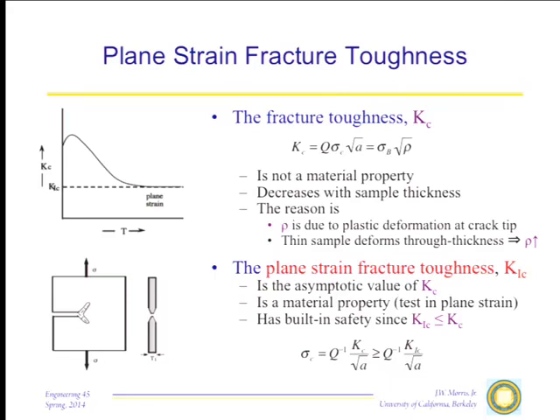If I take a sample that is very thin, then I can always get plastic deformation here in the plane of my plate, coming off at 45 degrees, normal plastic deformation. If the plate is very thin, I can also get plastic deformation through the thickness of the plate. But that also wants to go up at 45 degrees, and as the plate becomes thicker, that shear line that I would have to deform on to get this thinning in the thickness of the plate gets further and further away from the crack, out of the material that's way out of the stress field. The consequence of that is that as this plate gets thick, I lose this lateral deformation, and all I have left is this deformation in the plane. That condition is called plane strain. All of the strain associated with the crack tip is in the plane because I can ignore the thinning in the perpendicular direction. When that happens, all of a sudden the thickness effect is going to disappear. The degree of blunting will be the same no matter what the thickness is, and I get a constant value. And that's called the plane strain fracture toughness, and that is a material property. And that's what people measure, and that's what people tabulate.